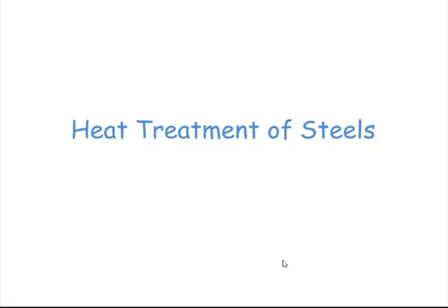the ductility and toughness. Tempering is also a kind of heat treatment, generally carried out after hardening treatment, because after hardening you get high hardness and high tensile strength. We do not want such a high hardness component in the application. So generally we reduce the hardness by tempering. Again, the purpose of tempering is not to improve the hardness but to improve ductility and toughness.